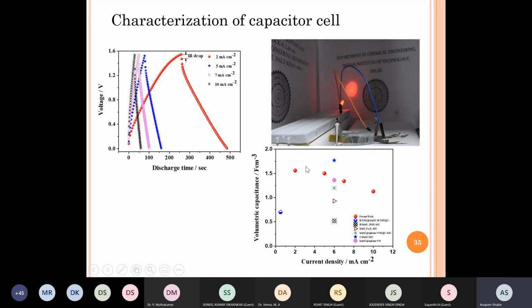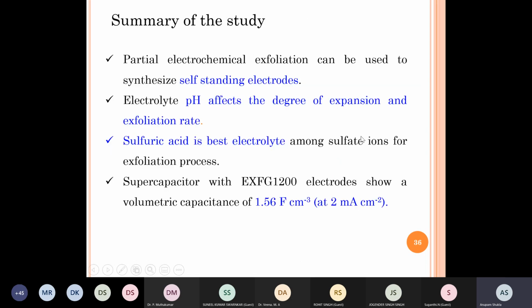We just look compared with literature where our capacitor is in terms of volumetric capacitance. These are some of the best values reported in literature. The red balls here are the performance of our capacitor, and of course it is comparable with literature. Here we combined 3 capacitors in series so that the voltage becomes high enough to light an LED. So this is a photograph showing an LED which was powered by the capacitor.